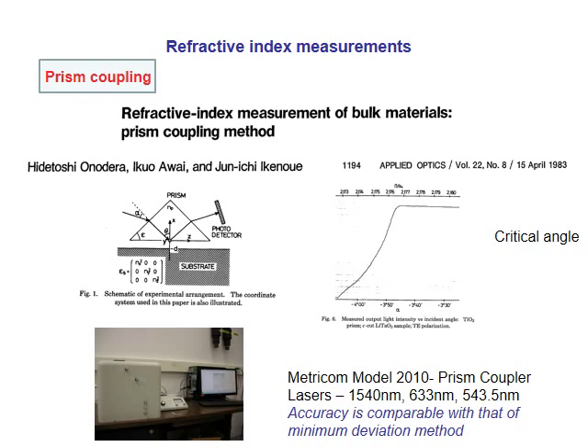This is the prism coupling method. A prism is coupled to the sample surface. Laser light incident at the prism surface at angles lower than the critical angle will lead to total reflection of the light and maximum light intensity at the detector. By changing the angle of incidence of the laser, when the critical angle is reached, light will enter the sample, and therefore the intensity of the light at the detector falls down.